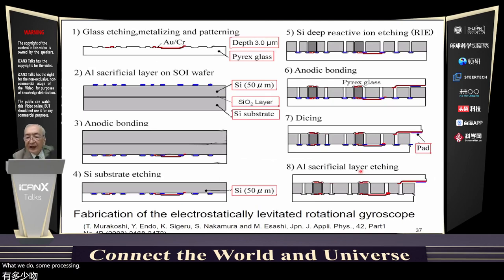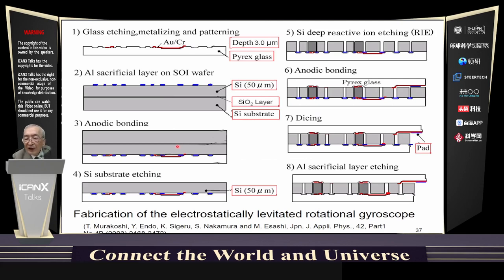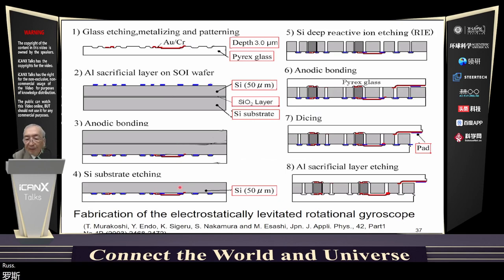Fabrication process of the electrostatically levitated rotational gyroscope is shown in this slide. Aluminum is patterned on a silicon on insulator SOI wafer in two. After anodic bonding to the glass, the silicon substrate is etched out in four. Grooves are made by deep reactive ion etching in five. After another glass is anodically bonded on it, the wafer is diced. Finally, the aluminium is etched out and the rotor is released to rotate.